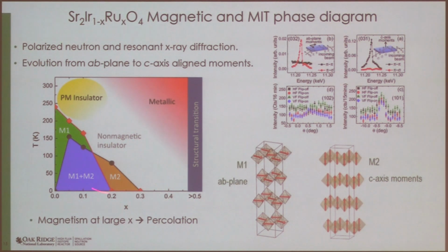So we looked for any type of structural phase separation. There was no evidence of that from neutron or X-ray scattering. We don't see doubling of 2 theta peaks. So we believe that this is most likely electronic phase separation that has been found in the 327 as well. And this is causing a very unusual phase diagram.